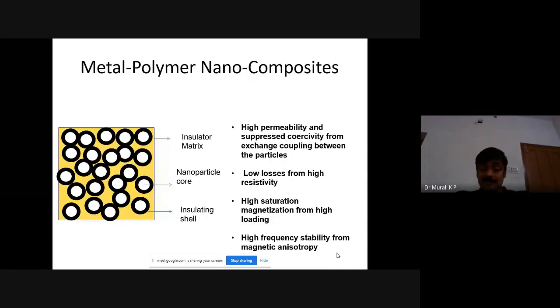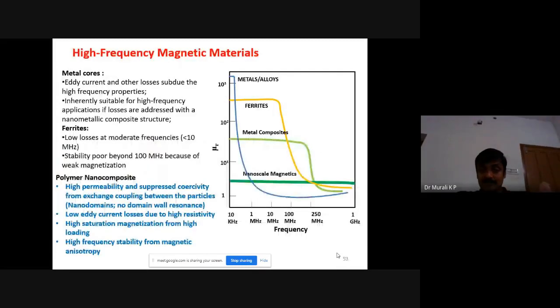And we will get high saturation magnetization from a high filler volume fraction. And we can create frequency stability by fabricating a magnetic anisotropic structure. That also I will explain, how we can make it. So these are the comparisons of different materials with frequency. As you can see, nanoscale magnetics will give better frequency stability compared to others.